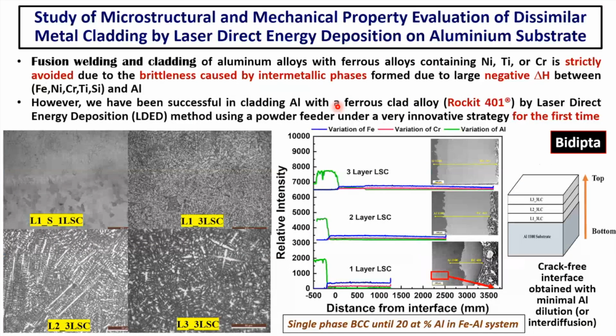Now this is also something interesting, as I was mentioning in the beginning, how you actually can override the thermodynamic constraints or kinetic constraints. We all know that if you try to fuse aluminium with iron, or aluminium with titanium, or for that matter nickel, or all these transition metals, they are bound to form intermetallic compounds and phases, which generally have higher melting point or higher fusion point, but more importantly have a complex crystal structure, as a result of which they introduce high strength but very large brittleness.